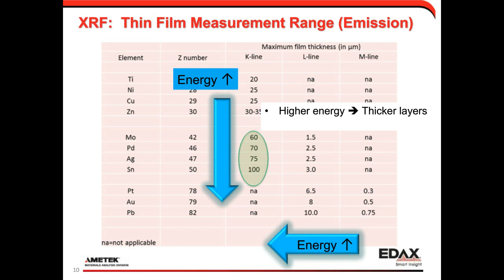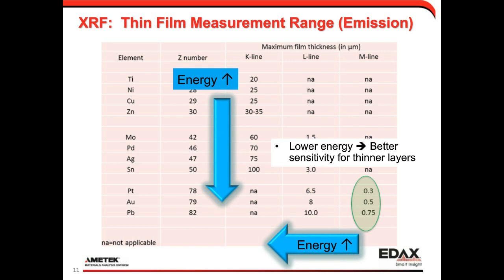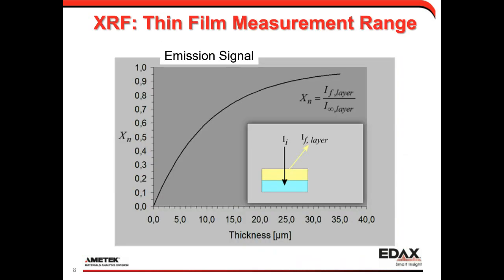Now, the lower energy line series also have uses. You'll see, for example, for the M lines, you measure up to a half micron or 1 micron and less. What these line series do give you is they're much more sensitive to thinner coatings. So the way that works is that instead of having this emission plot running from 0 to 40 microns, it runs from, let's say, 0 to 1 micron. And then you have 80% being the useful region of the signal that you can use to make measurements. You have 80% of that range of XRF signal applying over 1 micron of thickness.